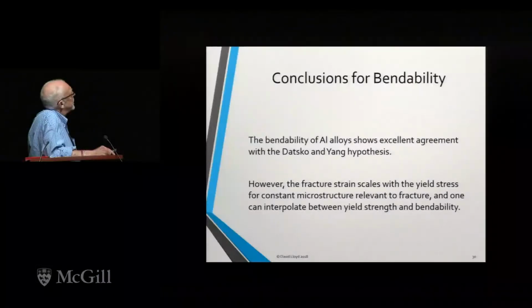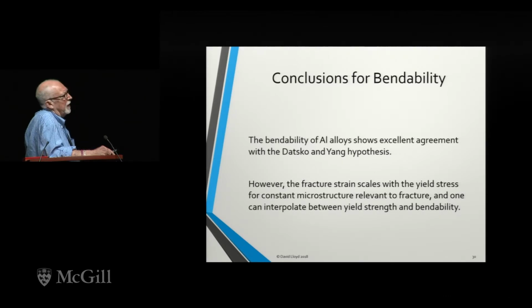Now, in addition to that, the fracture strain scales with the yield stress of the material for a constant microstructure relevant to the fracture process. And by that I mean it's not the general microstructure, it's what bits of that microstructure are relevant to the fracture process. And if you change the strength while keeping those parameters in the microstructure constant, the fracture strain will scale with that.